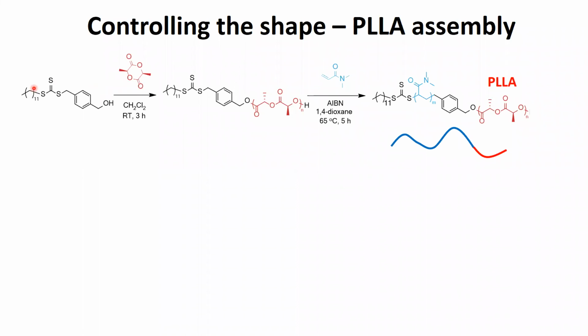This is really the only chemistry slide I guess I have, but this is how we make our polymers. So we start off with what we call our initiator. We polymerize from this hydroxy group to form, first of all, our lactide block. We then use this trithiocarbonate group to polymerize the second monomer. So we end up with this polymer chain that has this short red block, our short polylactide block, and then a much larger dimethyl acrylamide block, which is water soluble.